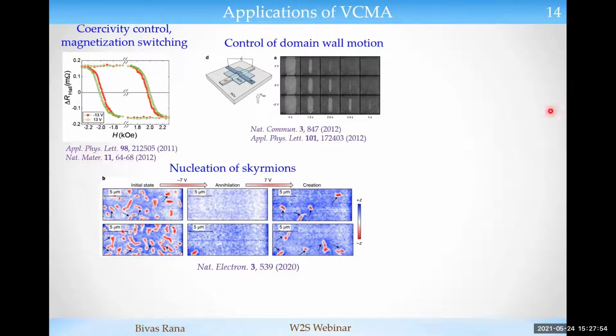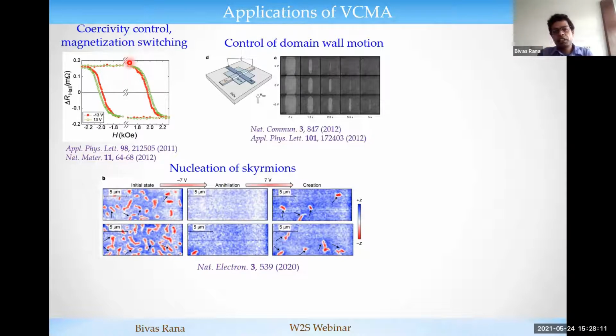So now I will talk about the application of voltage control magnetic anisotropy. People started to apply this voltage control magnetic anisotropy to tune basic magnetic properties, like control of the coercive field or switching the magnetization by applying the gate voltage. Also, you can control the domain wall motion by tuning the anisotropy by gate voltage. Not only that, people have shown that this VCMA can be a nice tool to annihilate or to create magnetic skyrmions, which is quite interesting nowadays.